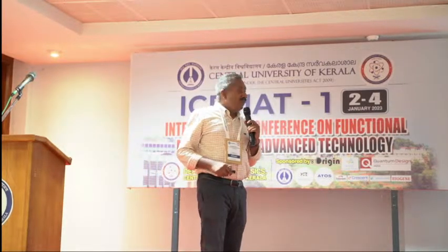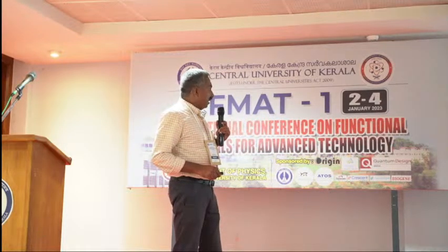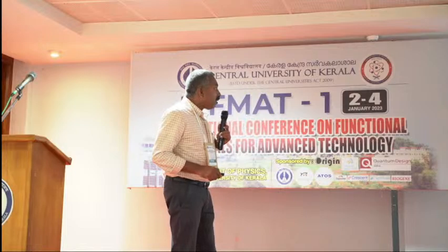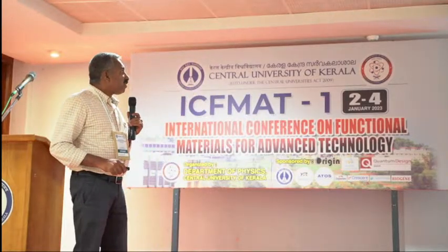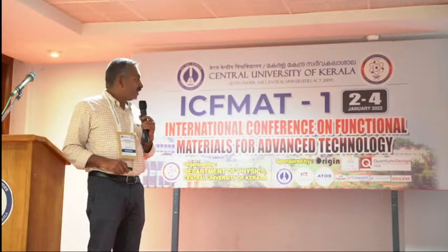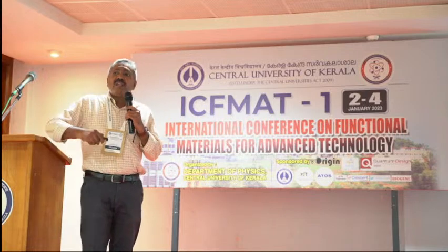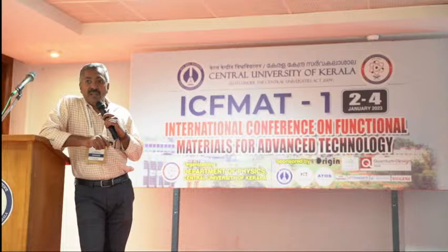We also need to look at the symmetry considerations. For example, the crystal lattices of graphene and TMDC belong to different space symmetry groups. The graphene lattice belongs to a D6H point group, which makes it a centrosymmetric material. And we know that when a material is centrosymmetric, it is not possible to have second order nonlinearity.